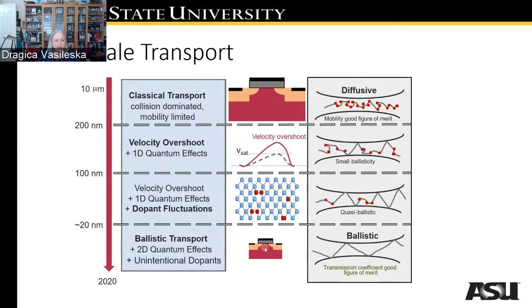Things get further complicated in the nanoscale regime. For example, if we look at devices with channel lengths larger than 200 nanometers, we have classical transport, which is collision dominated. We call that diffusive transport. It is mobility limited, so mobility is a good figure of merit. Below 200 nanometers, velocity overshoot and one-dimensional quantum effects start to dominate the device behavior. Velocity overshoot is an effect in which the carrier velocity reaches values in the channel that are higher than the saturation velocity, and therefore the device exhibits small ballisticity.